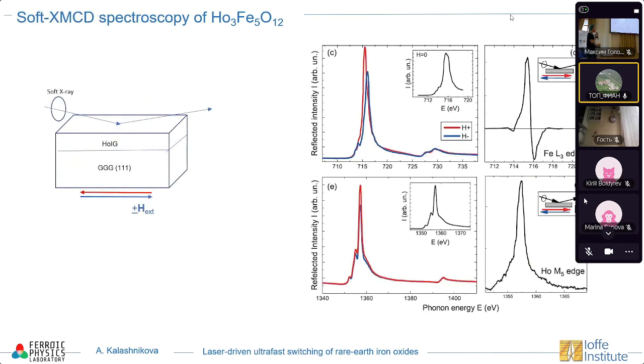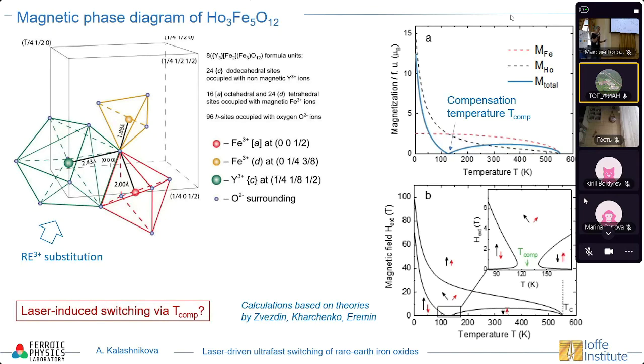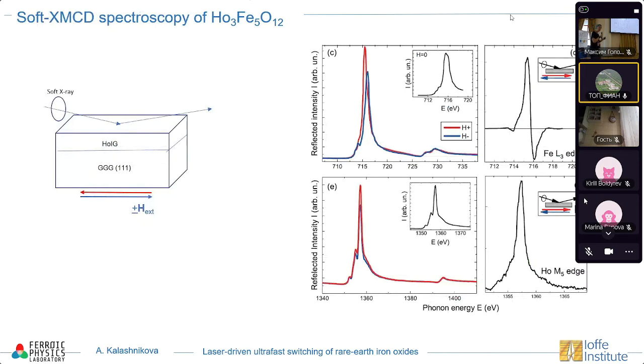We wanted to really study it, but this time by looking separately at rare earth and iron magnetizations. And for this, we of course needed something sensitive to different magnetic moments. And this is XMCD in the soft X-ray range. Basically, here are shown the reflected spectra for circularly polarized soft X-rays at energies around 715 electron volts.